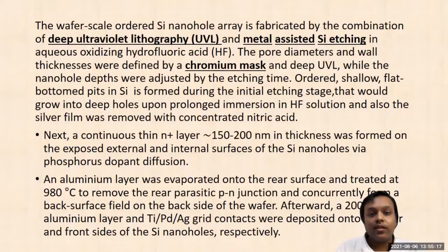These arrays are fabricated by the combination of deep ultraviolet lithography and metal-assisted silicon etching in aqueous oxidizing hydrofluoric acid. The pore diameters and wall thickness were defined by a chromium mask.